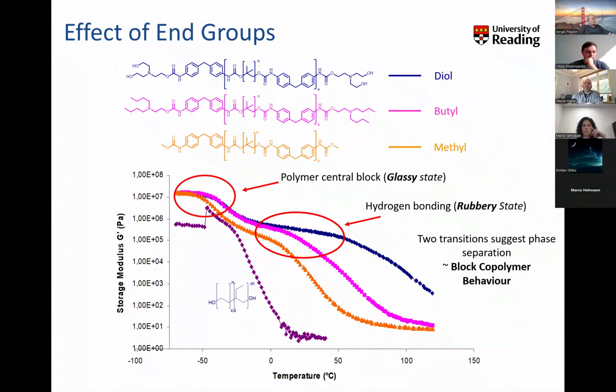What you can see is that for the polyurethanes shown in blue, which is the diol end group, the butyl in the pink, and simply end capped with methyl in the more tan color there, you have very different rheological characteristics. These materials are behaving like block copolymers, where there's a polymer glassy state below zero, but as you increase the temperature, you simply don't get complete flow directly. You have this rubbery state where the rheological characteristics are maintained in terms of the storage modulus. This is characteristic of block copolymer behavior, and it indicates that there's quite a reasonable degree of organization within these materials in the bulk state. I'll talk about that in a bit more detail in a few slides' time.